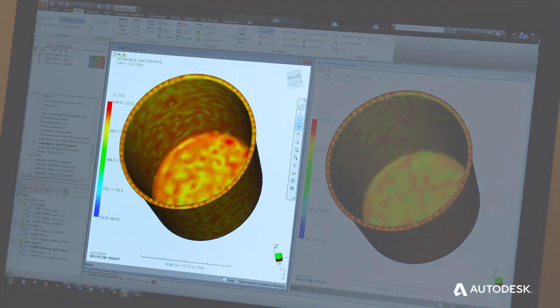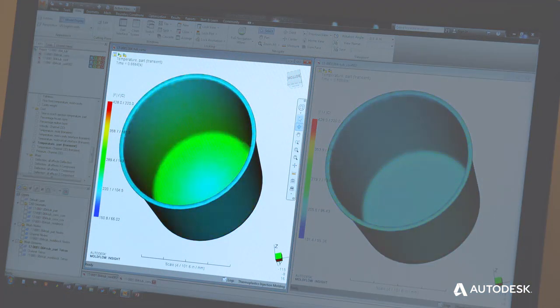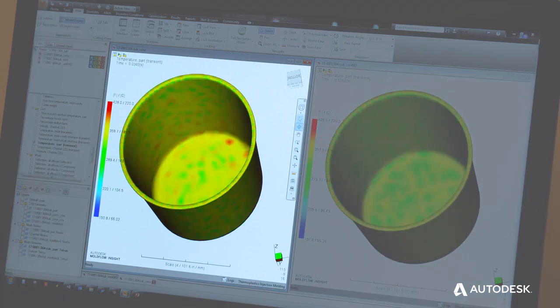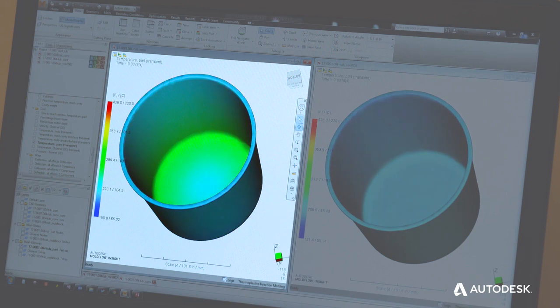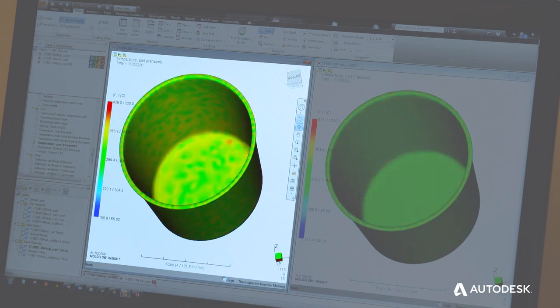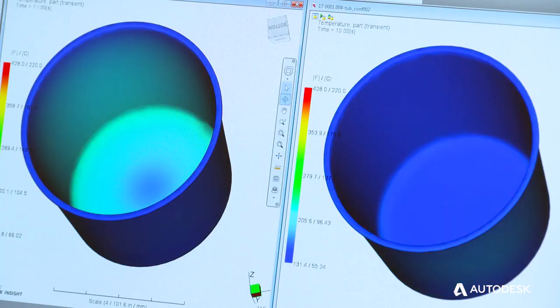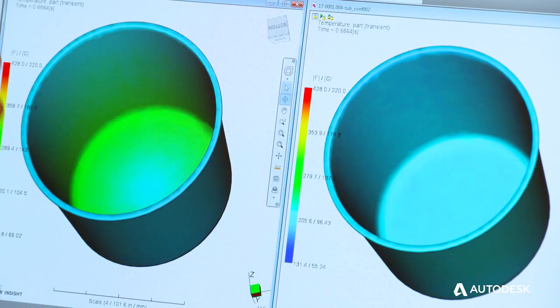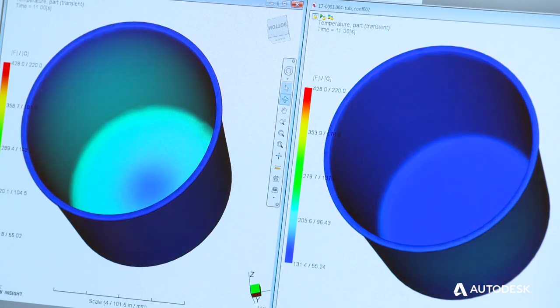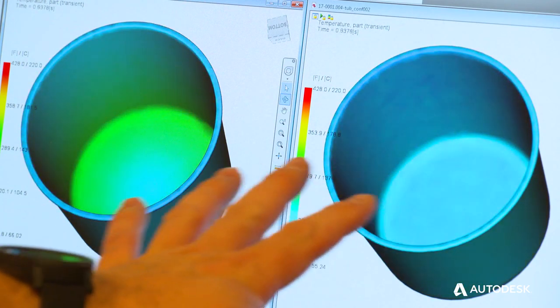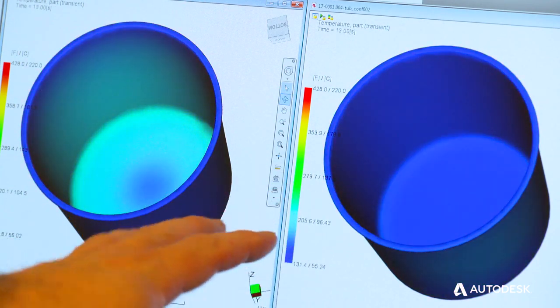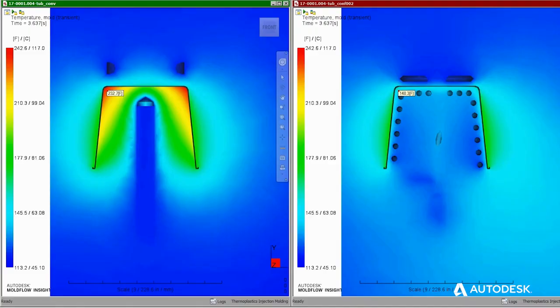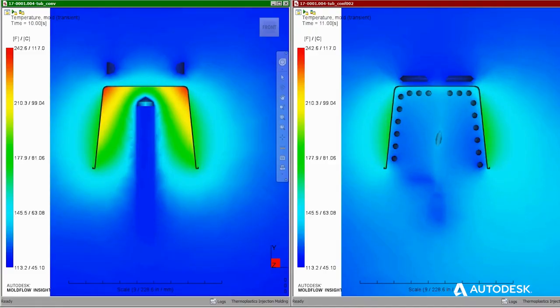The problem with this is the bottom of the bowl was warping severely, so they couldn't shorten their cycle. They were pretty much already at their minimum capacity. What we did was we ran analysis on their existing water configuration, we implemented conformal cooling channels inside this dome here, and we were able to reduce their cycle by almost 25 percent by reducing their cooling portion.